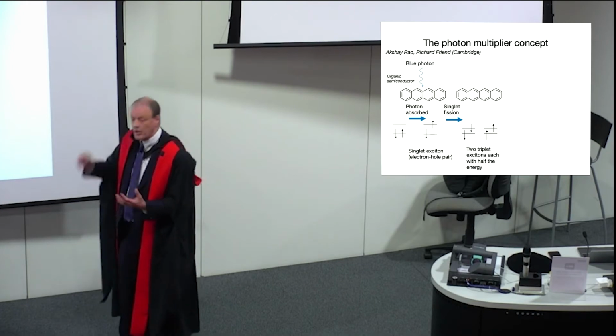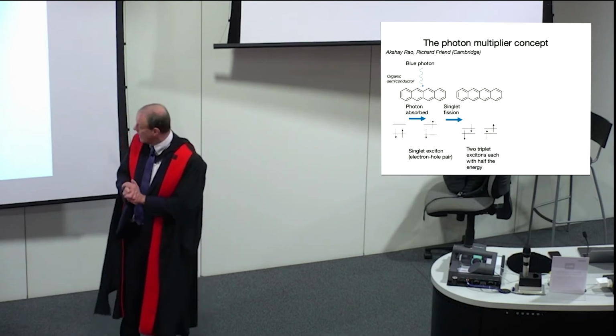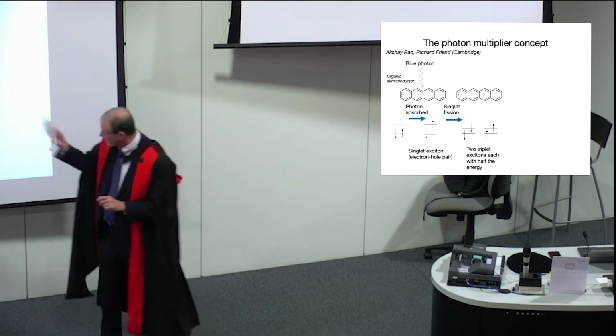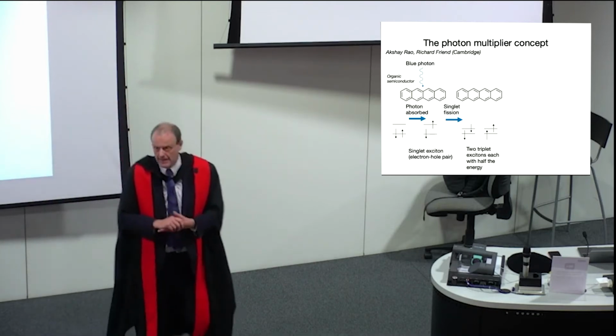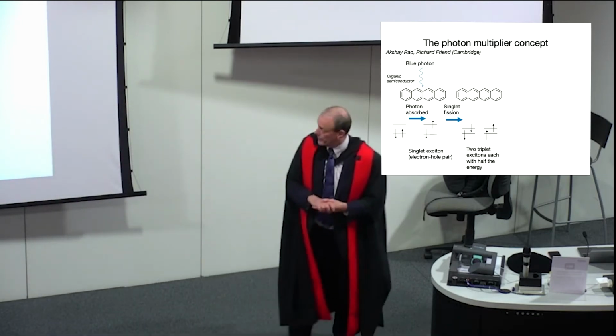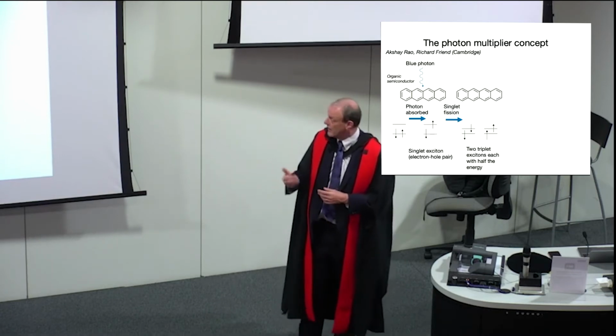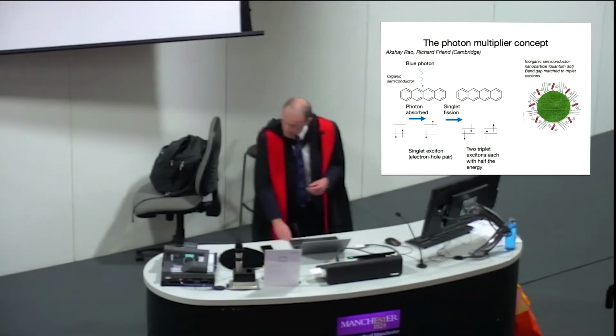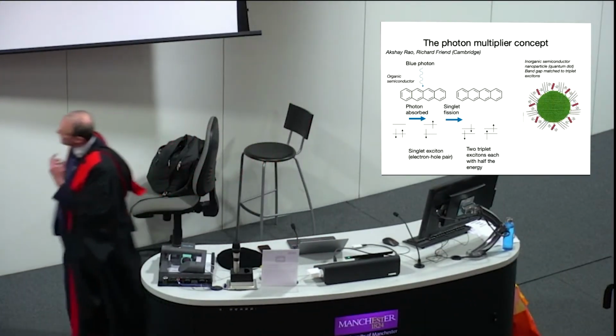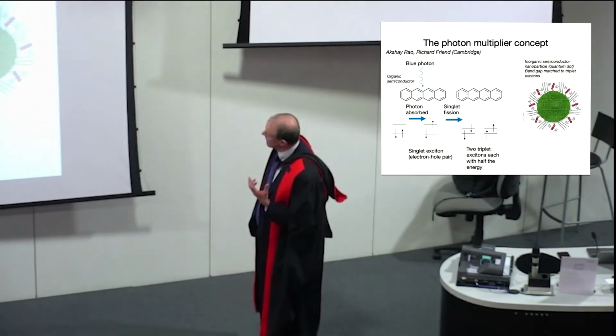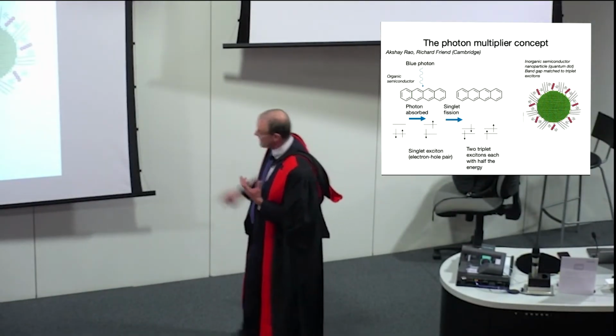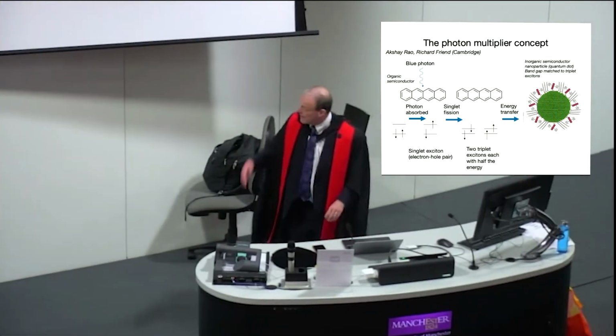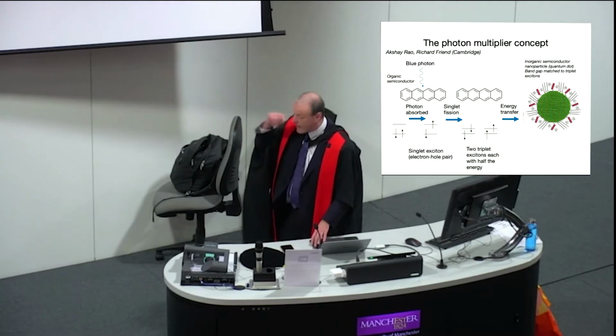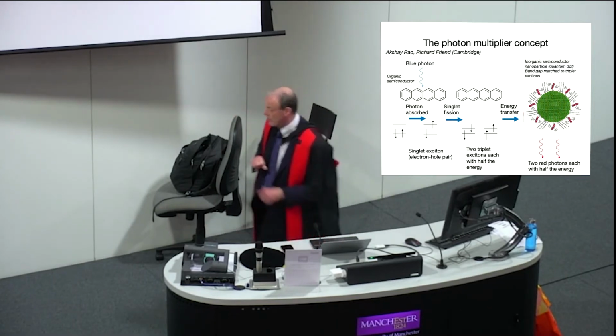The triplet excitons can't recombine to make a photon because of the selection rules that come about from their spin state. So they just sit around doing nothing and eventually decay non-radiatively, so it's wasted into heat. But what Akshay and Richard realised is that if you put next to this a quantum dot, an inorganic semiconductor nanoparticle, where you match the band gap to these triplet excitons, then the electron and the hole can hop into there, they can transfer the energy, and there they can happily recombine, and they can make two red photons with